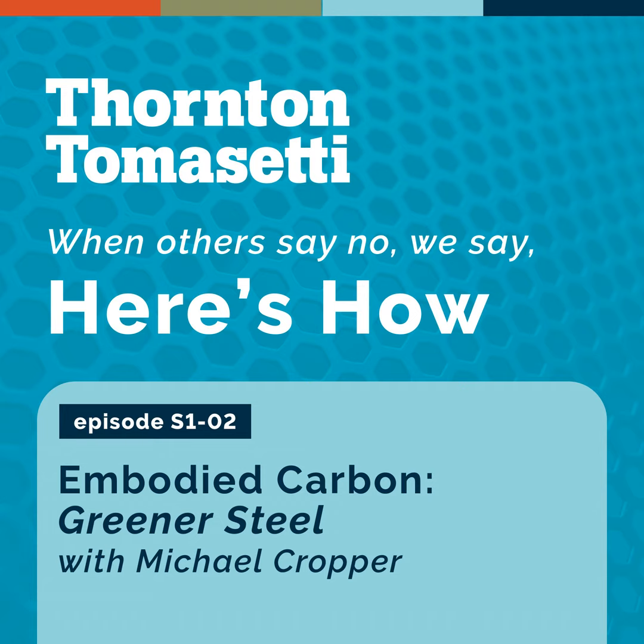We do. There are two main ways that steel is manufactured. The first is the basic oxygen furnace, or BOF, process, which is used in about 70% of global steel production. It's also known as extractive steelmaking because it uses primarily raw materials. The second way is the electric arc furnace, or EAF, process. EAF uses up to 99% recycled steel, so it's known as circular steelmaking. It typically has just a third of the carbon footprint of steel produced with BOF.